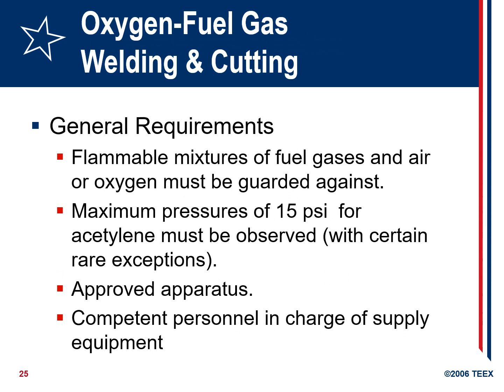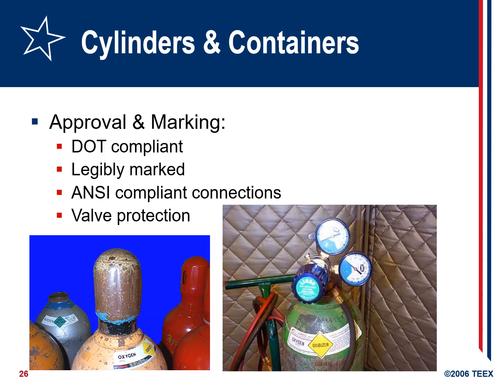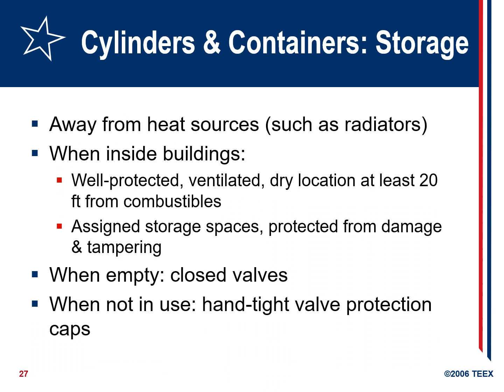For oxygen-fuel gas welding and cutting, flammable mixtures of fuel gases and air or oxygen must be guarded against. Maximum pressure for acetylene must not exceed 15 psi. Acetylene must be used with approved apparatus under a competent person in charge of supply equipment.